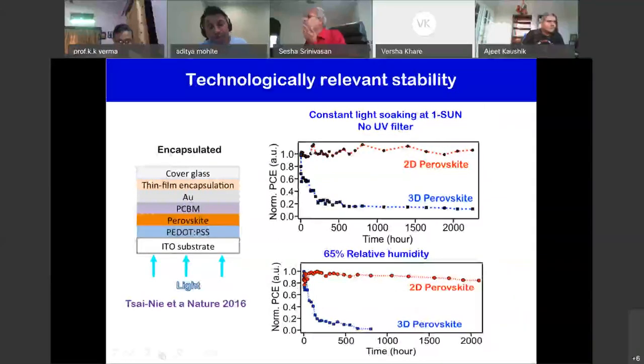Okay, and so here's a slide which is showing you devices under continuous light and over 2000 hours of stability. And so you see, compared to the 3D perovskite, these are way more stable. This is a device at about 65% relative humidity. And so this has really triggered a big field in itself, where people are now really working on this material and trying to use it in different types of applications, exploring the physics of this.